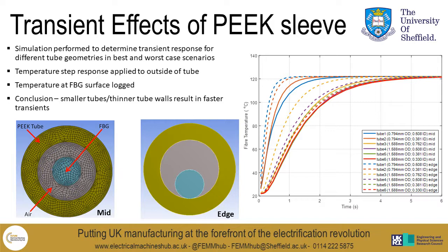That can be attributed to the fact that obviously the larger tube has a larger thermal mass, so there's more of it to heat up. What you can see is regardless of which tube is selected, the transient response is still under about 5 seconds, which, when you consider the thermal mass of an electric machine, should be adequate. The other thing to notice is when you look at the smaller tubes, that can be dropped down to 3 seconds at the most.